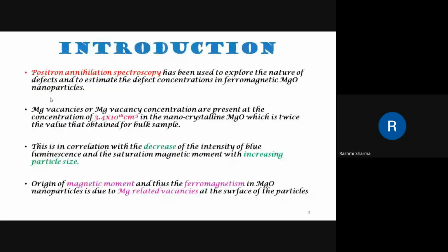In order to prove the existence of ferromagnetic property in magnesium oxide nanoparticles, positron annihilation spectroscopy was used. This positron annihilation spectroscopy has been used to explore the nature of defects present in the magnesium oxide particles and to estimate the defect concentrations. Using this technique, what they found was that the magnesium vacancy concentration is 3.4 × 10^16 per cubic centimeter in the nanocrystalline magnesium oxide, and this value is twice the value obtained for the bulk sample. In optical spectroscopy, there is also a decrease in the intensity of photoluminescence and the saturation magnetic moment.